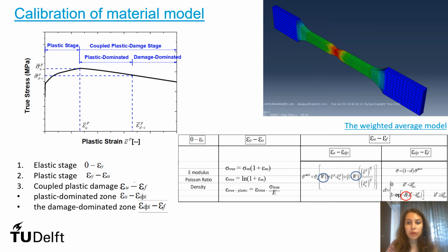To calibrate the material model, in the elastic stage, I introduced the E modulus, Poisson ratio, and density obtained from the test. In the plastic stage, I calculated the true stress and the true plastic strains, and then in the coupled plastic damage zone, I used the weighted average model, calibrating parameter W, the weight parameter, and parameter V that best describe the damage.